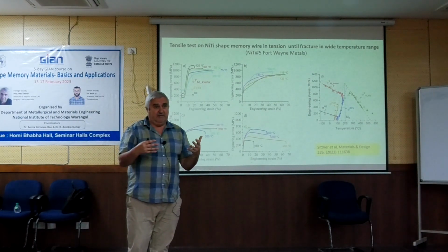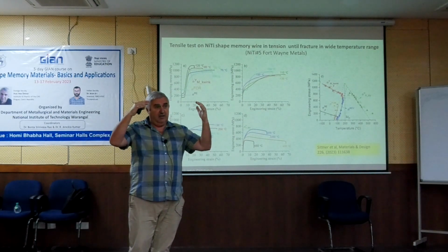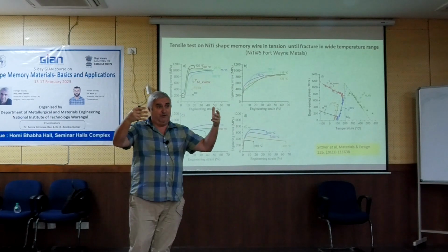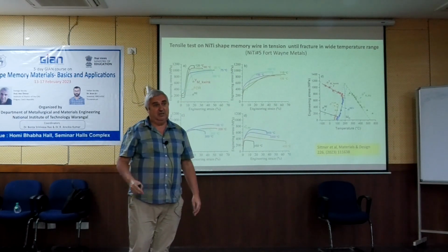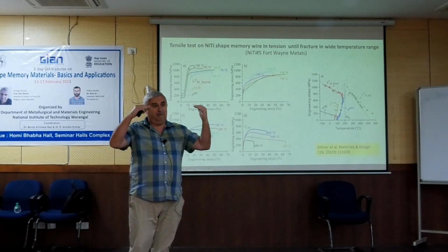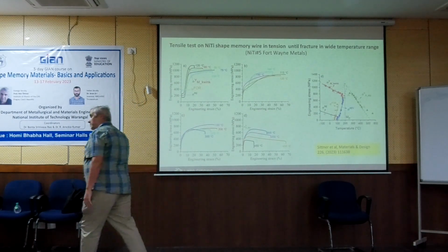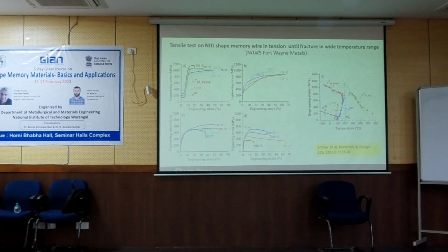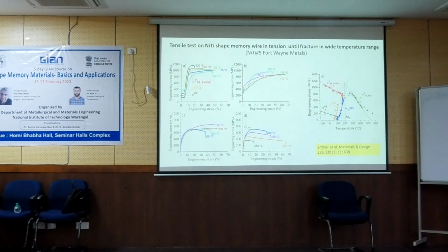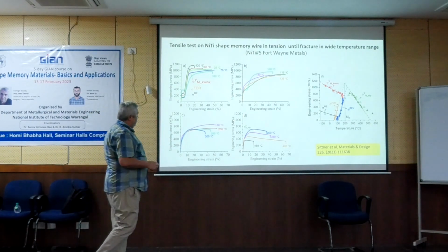But on superelastic wire, if you heat it to 100 Celsius, the stress is like 600 megapascal, lots of martensite deforms plastically, and it's irrecoverable. So this is the reason for developing the high temperature shape memory alloys, because they have higher AF temperature, and we can have superelasticity at 200, for example. This is very, very nice.